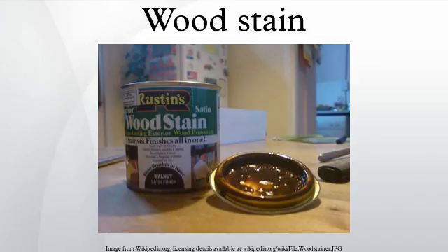End grain and bias cut grain are far more absorbent, thus will accept more pigment and will darken considerably in those areas. The hard ring may absorb differently from the soft ring. The characteristic medullary rays in oak will absorb much less and remain mostly blonde. Woods that have been heavily subjected to paint strippers or washed down with detergents or solvents will have an increased open grain and accept substantially more stain than normal. Woods from different species of trees can have huge variations in how well they take stain.